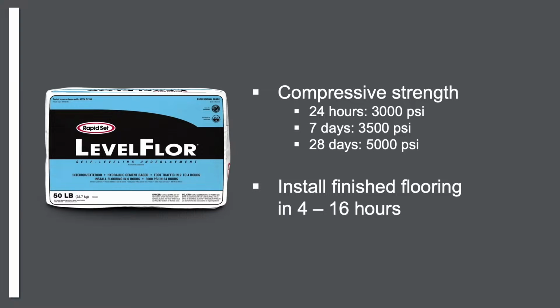Now, no water curing is required on the level floor. It contains self-curing technology, so it can hold on to that water and get all of the proper strength that it needs. And it can achieve 3,000 PSI in 24 hours and will exceed 5,000 PSI in 28 days.